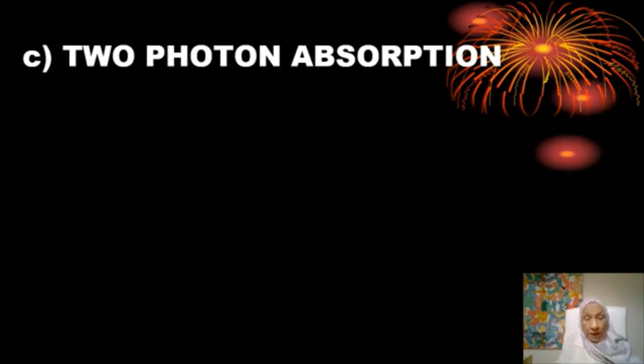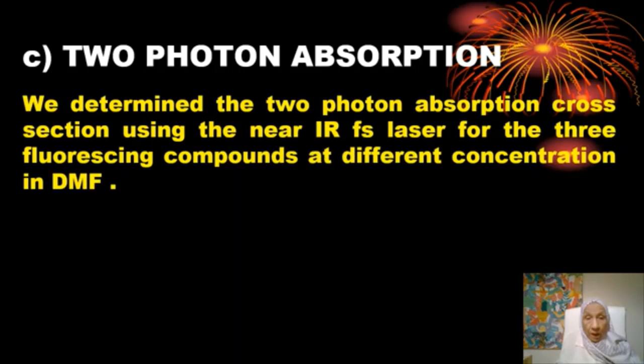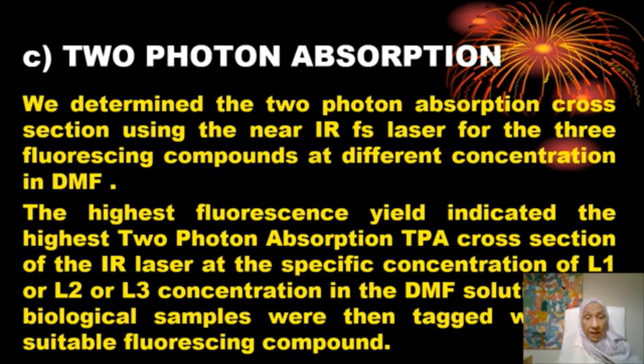So instead of the sample absorbing one photon, it would absorb two photons. We measured the two-photon absorption cross-section using the near-infrared femtosecond laser for the three fluorescing compounds at different concentrations. The highest fluorescence yield indicated the highest two-photon absorption.